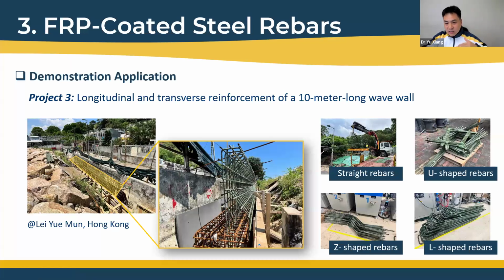Besides, I need to explain one point - the fiber. For these rebars, the fiber is mainly along the hoop direction. So when we do the bending, the separation is just between the fibers. So this will not affect the coating, cause rupture, or break.